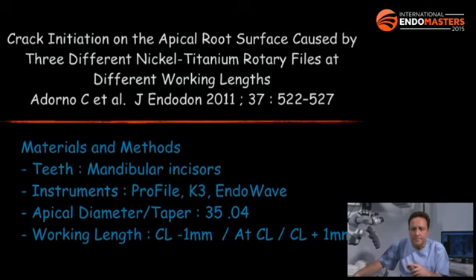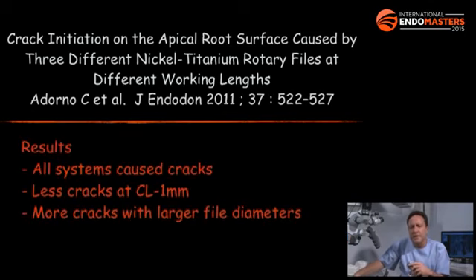What did they find? And just remember, all these files are used in continuous rotation. They found that first, all systems caused little micro cracks. Second, that you had fewer cracks if you were working short. And third, and very important, they found that you had more cracks when you enlarged with bigger diameters apically. So just keep this in mind, because the same people who are telling you not to use reciprocation because you create cracks are telling you that you should enlarge at least to 35 or 40 in rotation.